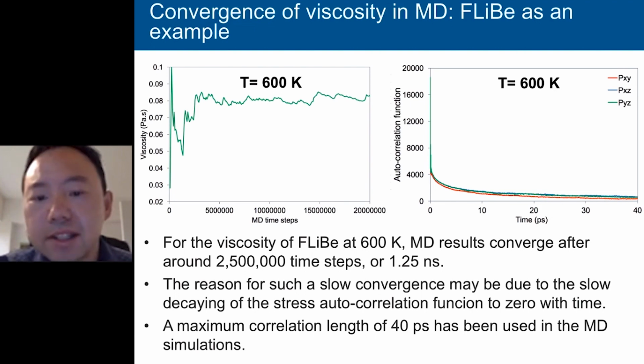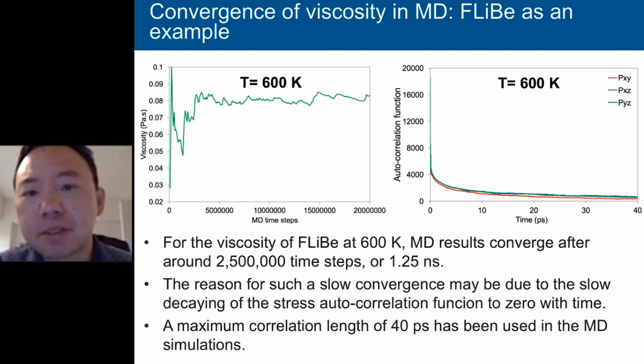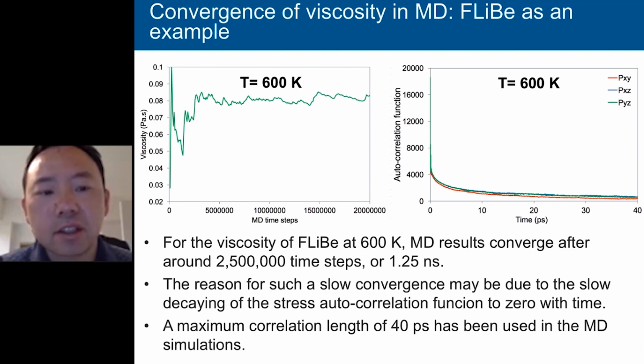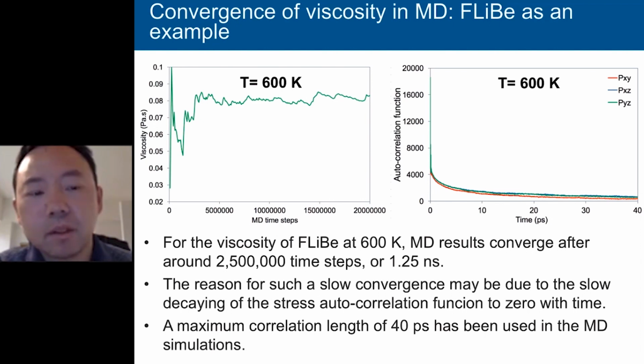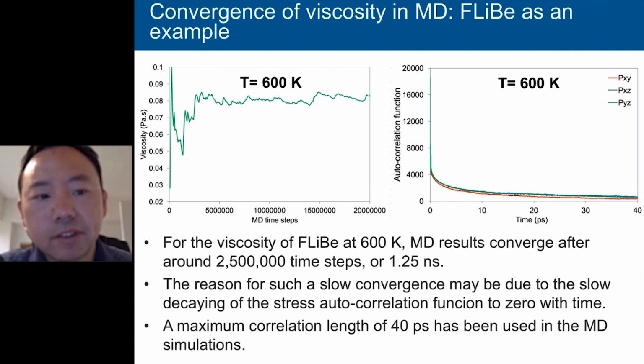So this is an example I used to show the convergence of viscosity with MD time step. I used the FLiBe salt as an example. So the left figure shows the MD calculated viscosity of the salt as a function of time step. You can see that the convergence will occur after about 2 million time steps, or about 1 nanosecond. So that's why classical MD will have to be used in this scenario in order to get statistically accurate